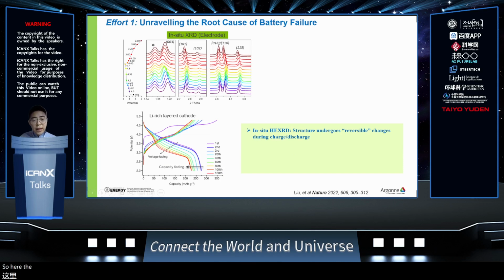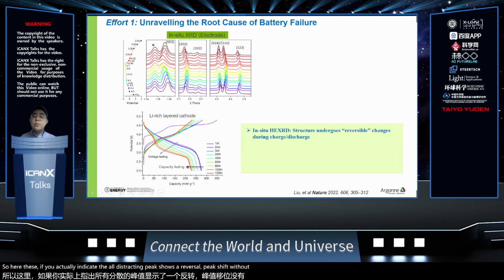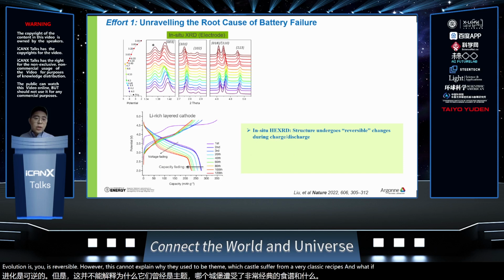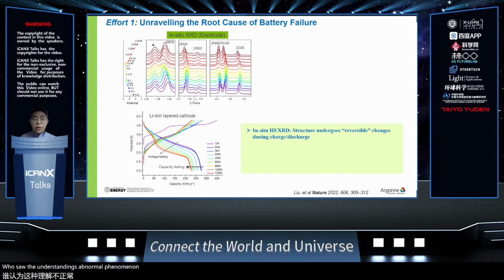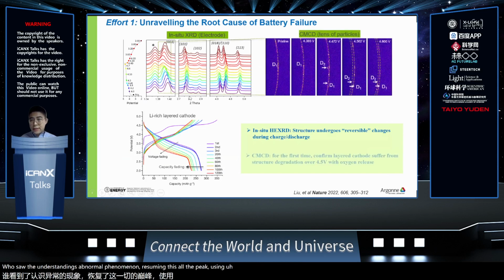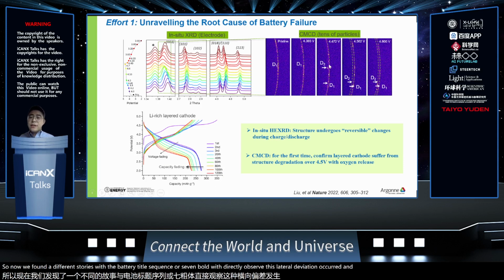Here the in-situ XRD indicates that all diffraction peaks show a reversible peak shift without any new peak generation. This seems to suggest the structure evolution is reversible. However, this cannot explain why this lithium-rich cathode suffers from very fast capacity fading and voltage fading. To further understand this abnormal phenomenon, we zoom in on this O3 peak using the CMCD. So now we found a different story. When the battery is charged to 4.47 volts, we directly observed structure degradation, and this exactly matched the oxygen release as reported previously.